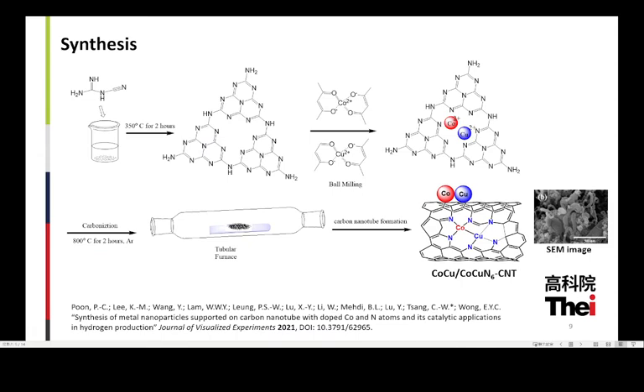To synthesize the cobalt-copper catalyst, the first step is to place the dicyandiamide in a muffle furnace at 350 degrees Celsius for 2 hours. Then we get the carbon nitride and we mix the cobalt and the copper through the ball mill process, and finally the mixture will be placed into a tubular furnace to carbonize it under 800 degrees Celsius for 2 hours. Then finally the carbon nanotubes are formed, and the structure of the catalysts is shown in the SEM image.